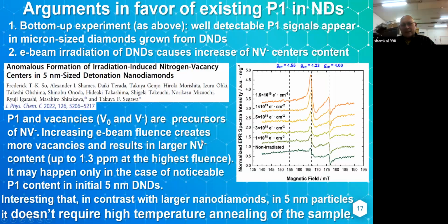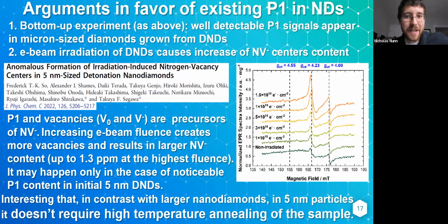Okay. Yeah, it's rather interesting. I thought maybe how did they explain this mechanism? They are proposing some band bending model at the surface, but that's kind of my general understanding at the moment. I don't understand it in great detail yet, but I will say that I've also done the silica coating and observed similar results on some, say, 40, 50 nanometer HPHT particles. Yeah, you see this big reduction in the intensity of this central line. I think it's in figure 2 actually in that paper. You can see these EPR spectra.